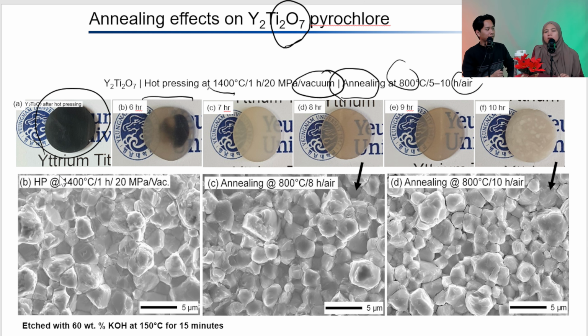Is it possible that the oxygen will come back? Yeah, because air contains around 20-something percent oxygen, right? So the oxygen lattice will be restored by annealing in air. We can see that transparency started to appear in this sample after annealing for 6 hours, and achieved the highest transparency after 8 hours. The transparency starts to decrease again after 9 and 10 hours.